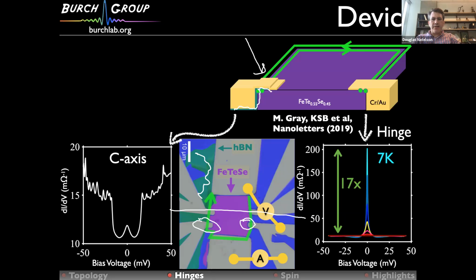Ken, I'm just trying to understand the units on the y-axis here. So what if I converted this into an actual resistance, what would the number be? 10 ohms, maybe 15. Okay. They're very conductive. We always get very conductive contact. So it turned out, for reasons we didn't know at the time, one advantage we have over others is that we're doing photolithography. So it turns out the E-beam damages. So we do photolithography and it seems to protect the system. We can get very good contacts fairly easily.